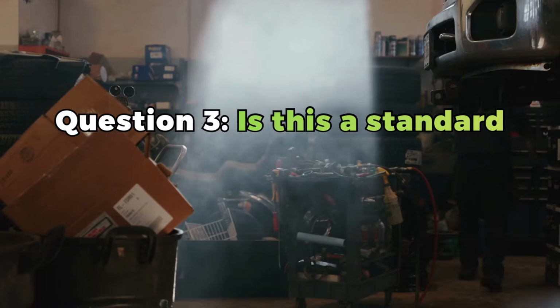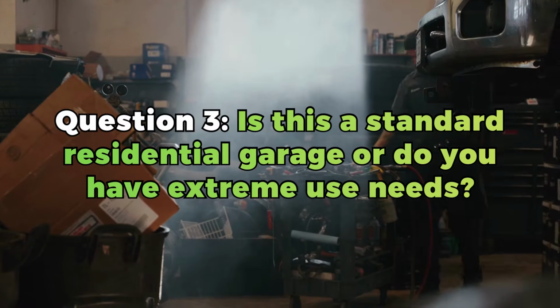Question 3, is this a standard residential garage or do you have extreme use needs? For slab-on-grade garages, which is almost all residential garages, moisture management is super important. Polyaspartic alone doesn't handle moisture very well. Most concrete sits at 7 to 10% moisture content, but polyaspartic manufacturers require less than 5% moisture for their warranties. Because of this, typical residential slab-on-grade applications require an epoxy moisture vapor barrier underneath, regardless of what top coat you're going to choose.